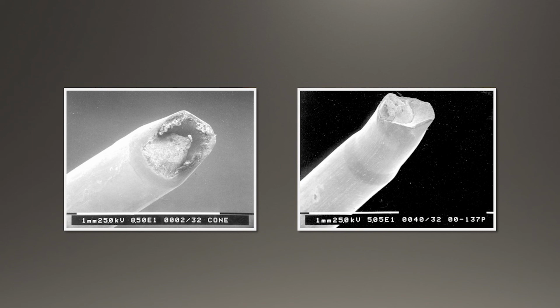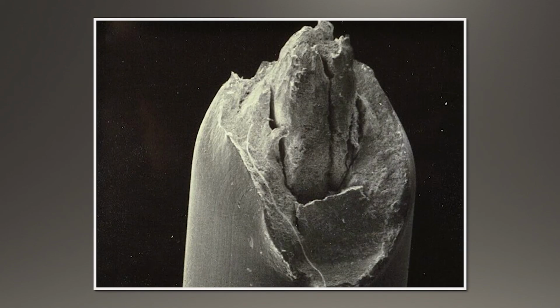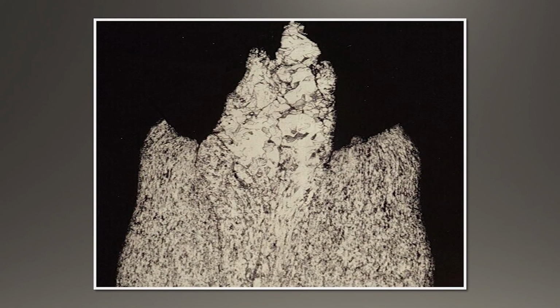This is the reason why I recommend that if you do get a break, you try and clean the wire with an ultrasonic cleaner to remove any residual drawing lubricant that might be present in a particular wire break. So here now you can see something else. Here there's an inclusion, and it's present inside what looked like some macro porosity break. If you make a cross section of that wire, you can see it's the original same structure, same copper that was being drawn, but this is the as-cast structure. So this particular inclusion fell into the melt, it went into the center, and during wire drawing, because it wasn't compressed as much during drawing, you can see some of the original shape of what that inclusion was.